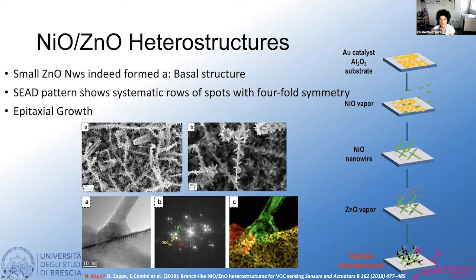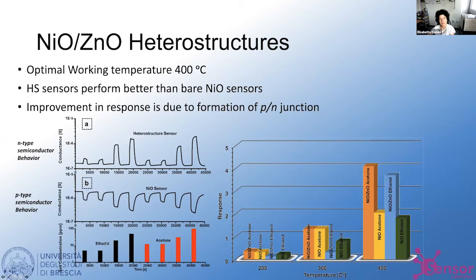What we have seen is that we have an epitaxial growth of zinc oxide over nickel oxide, also thanks to the very limited interface that we have between nickel and zinc oxide. When we look at the functional behavior of this heterostructure, we can see that nickel oxide, of course, is a p-type semiconductor. So as we introduce ethanol and acetone, we have a decreasing conductance, while in the heterostructure-based sensors, we have an n-type semiconductor behavior. So we have an increase of the response.